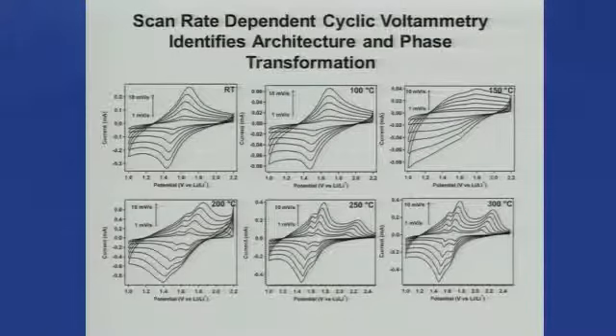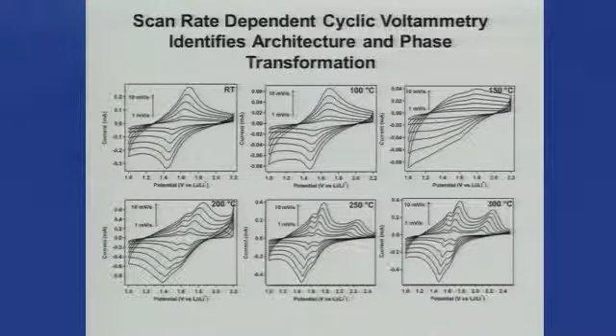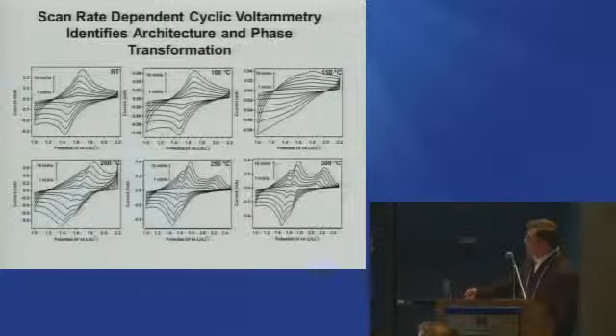But we found that we could make electrodes without any binder and look at the scan rate dependence for the nanosheet morphology converting into a nanoparticle and then the formation of anatase. So here shows the cyclic voltammetry of these thin film electrodes, room temperature, heated up, watch the growth of another peak growing in as evidenced by the formation of the nanoparticle morphology, and then start to see another peak out here, at a much higher potential, that's associated with anatase.